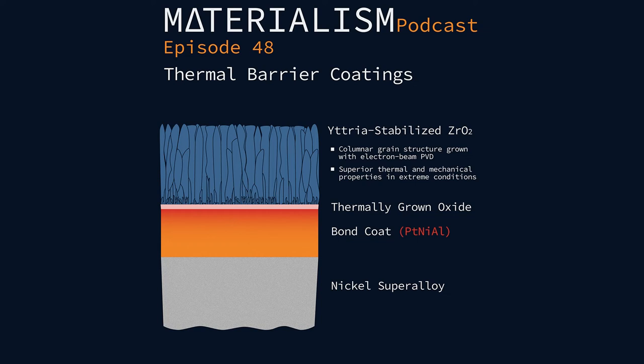Yeah, pretty cool. In one case, they were trying to understand, well, what's the cause of this? Why is this stress related to the thermal cycling? Well, imagine in the bond coat you had a bunch of aluminum. They added it intentionally because it would then grow to form a thermally grown oxide. Over time, that aluminum keeps on migrating to the thermally grown oxide layer. That thing grows. It grows slowly, but it grows. So you're losing aluminum from the bond coat, and as it leaves, that's putting it under compression, and it's putting the bond coat under tension. So you've got a mismatch right there. That's causing some of the strain.